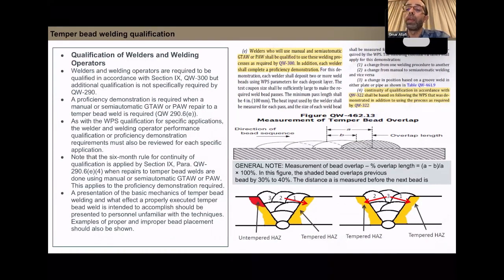Here, I would like to just cover that the continuity of qualification in accordance with QW shall be followed when using manual. So note that the 6-month rule for continuity is applied where repair of temper bead is done using manual or semi-automatic GTAW or PAW. So when you are using manual or semi-automatic GTAW, the 6-month rule applies, and you need to have a proficiency demonstration for all welders using manual or semi-automatic GTAW or PAW.